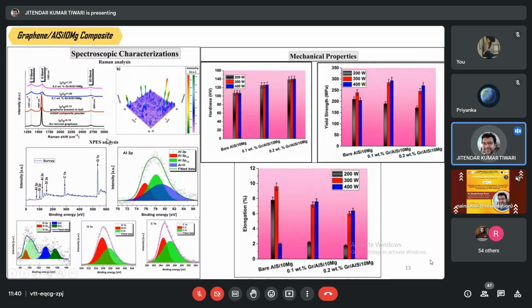Okay, so if you see the XPS results, I performed this analysis to understand how the graphene is reacting with the matrix material, and it is spectroscopically proven that it is not forming any kind of carbide. And there are some mechanical properties which are very important to understand. These fluctuations, I mean these random variations in results, are coming because of the presence of porosity. But if we compare the equivalent density samples, then we are getting around 21% increment in the yield strength.